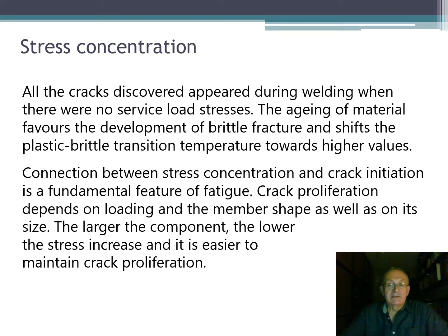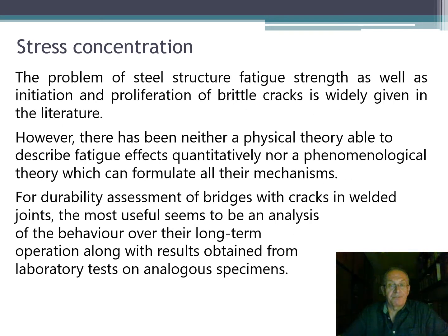The connection between stress concentration and crack initiation is a fundamental feature of fatigue. Crack propagation depends on loading and the member shape as well as its size. The larger the component, the lower the stress increase, and it is easier to maintain crack propagation. The problem of steel structure fatigue strength as well as initiation and propagation of brittle cracks is widely discussed in the literature. However, there has been neither a physical theory able to describe fatigue effects quantitatively, nor a phenomenological theory which can formulate all their mechanisms.